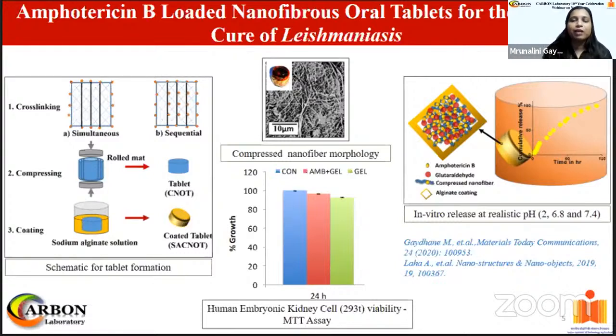the toxicity. At first, we accomplished the fabrication of amphotericin B-loaded gelatin nanofibers via electrospinning. The nanofibers were then cross-linked with glutaraldehyde vapors for a few minutes to improve their water stability. As the nanofibrous mat could have given fast release due to its high specific surface area, we introduced for the first time the compression of nanofibers into a tablet by using a hydraulic press and further coating the tablets with sodium alginate in order to impose drug diffusion barriers.